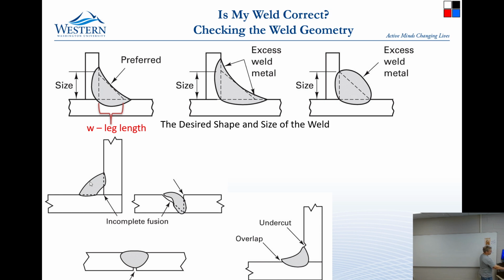Bridging is really easy to do when you don't get far enough down into the corner, and it can easily look like it's a good weld, and it's hard to tell that it bridged in the back. This happens a lot with beginning welding when people aren't willing to get their head down there and look really carefully where they're welding. It's also easy to not fill in all the way if you have a groove that you're supposed to fill in. And so this is something that you can go back and repair. The incomplete fusion is hard to repair without grinding everything all the way out.